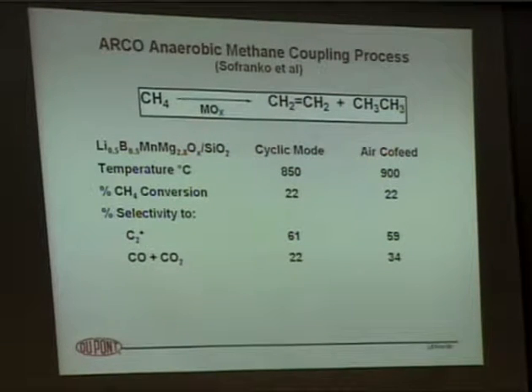I think the second biggest effort was done in the early to mid-1970s by Arco Chemical, John Sofranko and his group. They were looking at methane oxidative coupling to ethylene using a metal oxide catalyst. The composition here was a manganese-magnesium catalyst on silica with some promoters in there. This is an amazing reaction. It was run in a cyclic mode. The temperature was around 850 to 900 degrees centigrade. So they were cycling catalyst around the loop at nearly 900 degrees centigrade.